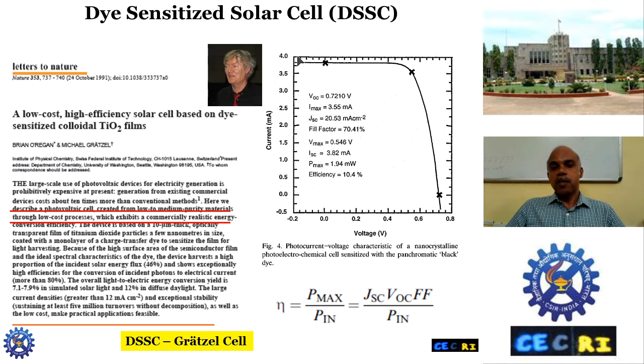So this is the IV curve of this cell developed here, and we can look at the open circuit voltage, which is 0.72 volts, and the short circuit current is 3.5 milliamps. So for this, the current density is 20.53 milliampere per centimeter square. With this cell, the efficiency obtained was 10.4%.